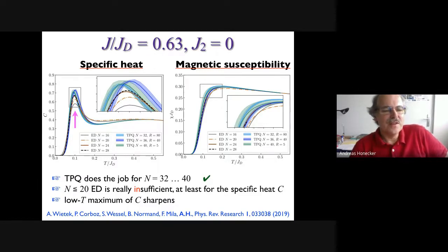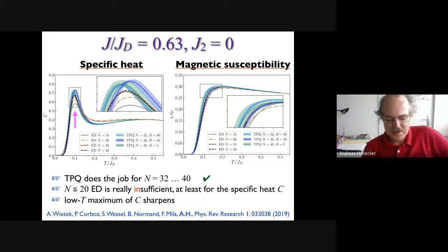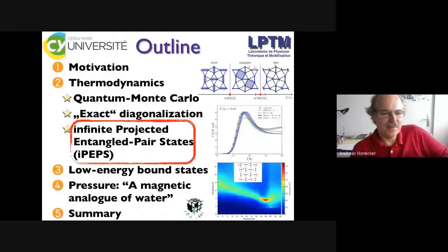You do see now finite size effects, but you can also see from the insets, at least here, that 40 spins for that particular ratio is good enough. So you need to go to 40, but that should do the job. 20, on the other hand, in the case of the specific heat, is not enough. From the point of view of physics, you do get a sharper maximum of the specific heat, and the edge here in the magnetic susceptibility does get sharper. So you actually do have a more pronounced low energy scale here than you had at weaker couplings.